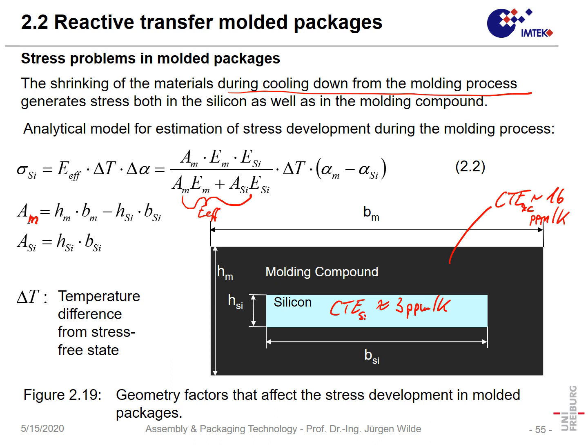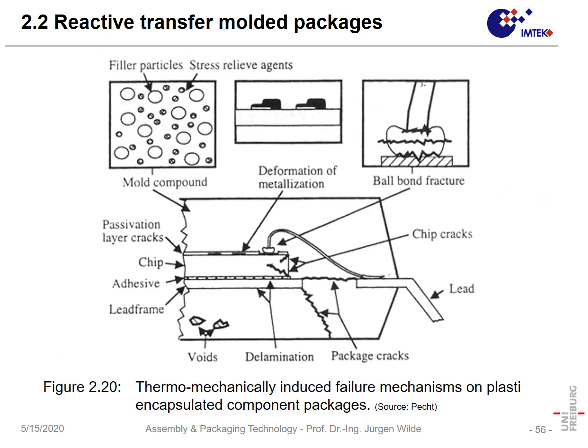The delta T is always measured against which point? It is either measured against the process temperature, or it is measured from the stress-free temperature. The stress-free temperature is not so easy to determine. In many cases, it can be the process temperature or the hardening temperature, but in some cases, it's just the glass transition temperature. Okay. Stresses are not only so-called global stresses as we have seen them, but we have also local stress effects.